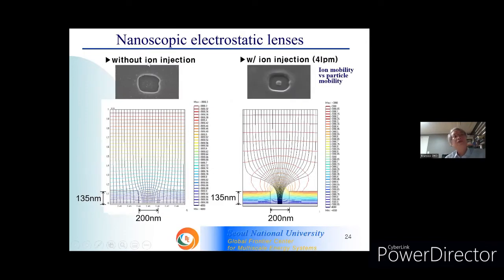So if we do not inject ion, particles deposit everywhere. Of course, since charged particles deposit on the surface of photoresist near the interface between photoresist and opening area, there may be some reason for focusing, but anyhow, particles deposit everywhere.